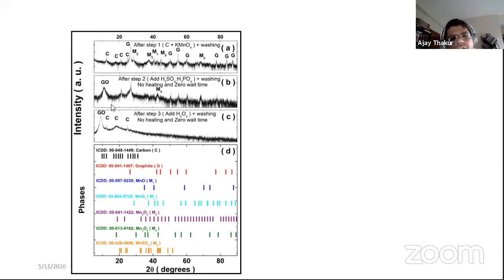And then via this, what we could zero in on was the most important steps which were relevant in growth of graphene oxide. Okay, and at the bottom, we are showing the ICDD stick diagrams for a variety of materials, starting from carbon, graphite, MnO, MnO2, all the other oxides of manganese, MnSO4, etc. And also the graphene oxide.